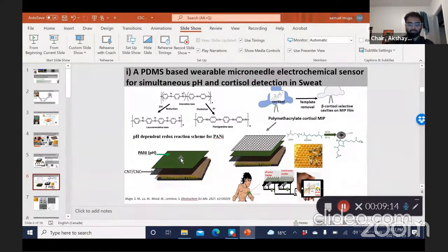And it's fairly well known that polyaniline essentially is pH responsive, because it interconverts between the emeraldine type of polyaniline and these other oxidized forms if you expose it to hydronium ions. And so we tested it to see if we can use it as a pH sensor. On the other hand, using the very same type of platform, and again we are printing it next to each other, so in parallel.